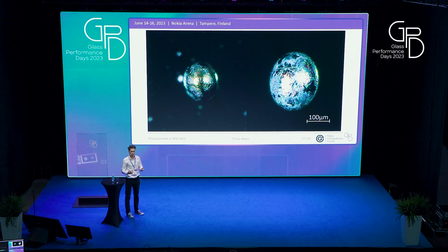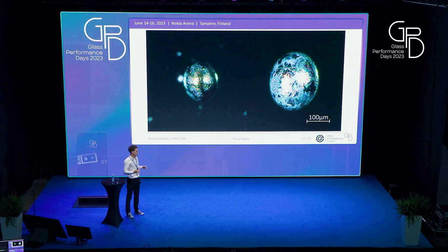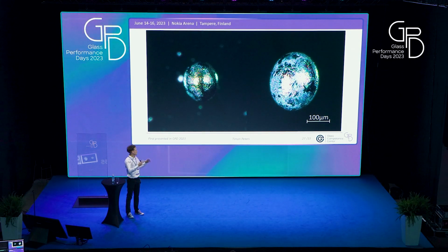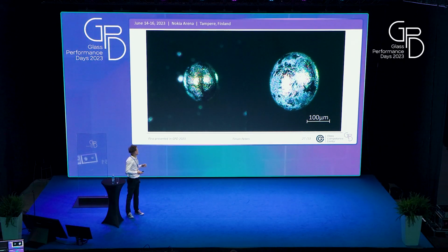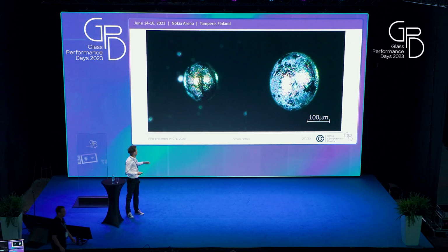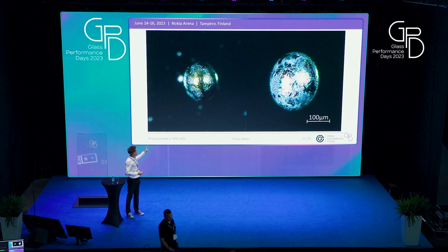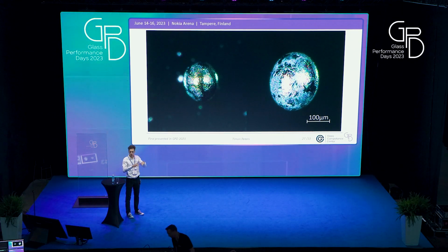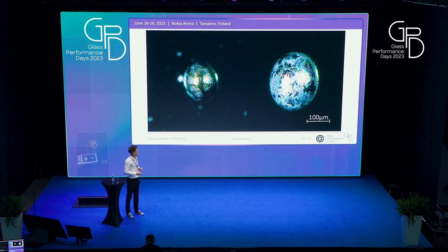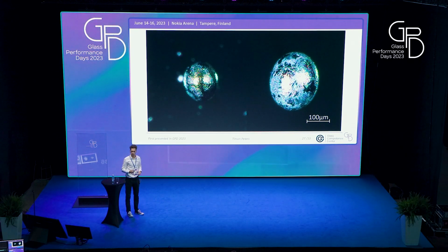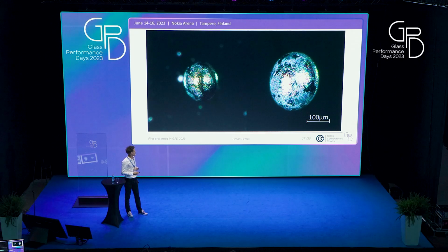Also, what you often find is, due to the fact that the thermal expansion coefficient of nickel sulfide is bigger than of glass, the inclusion will contract more than the surrounding glass, and a void will form around the inclusion, and this may fill with some kind of salt to a varying degree. On the left, it's just a bit, and on the right, the void is almost entirely filled with salt. So sometimes you also find that, and then you need to be careful when you try to identify the inclusion.